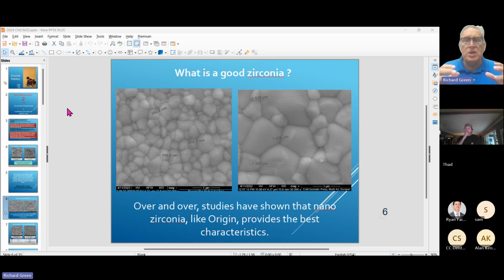So as you sinter your zirconia, it's shrinking down. It's trying to get rid of those voids, but it never can quite get rid of all of them, just because they don't like to go away. The particles can't fit as intimately as the smaller particles that we have here. And you can see that, here's a void, here's a void, here's a void, and all of those voids create opacity. They prevent translucency. And so by having those voids in there, that's another reason why everybody else's zirconia doesn't really respond well to rapid sintering. And that's a major thing.